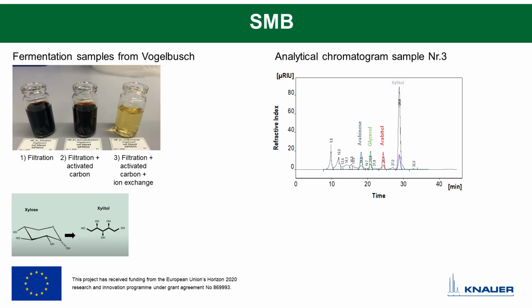KNAUER received 3 differently treated fermentation samples from Vogelbusch. These samples were from the xylose to xylitol conversion. The first sample was filtered after the fermentation, the second was treated with activated carbon after filtration, and the third sample was additionally desalted by ion exchange material.